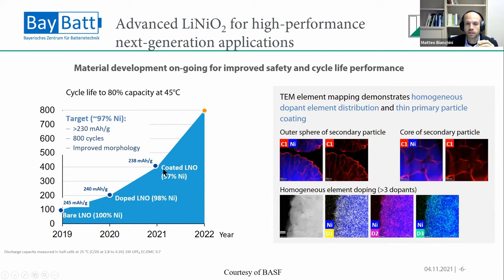And then what you absolutely need is also a coating. So as I mentioned before, you need something that will protect your surface from unwanted reactions. And this coating needs to be also highly engineered. So you don't only want to cover the surface of the secondary particles, but ideally you want to infiltrate the primary particles as well and be able to cover each and every primary particle to fully stabilize the material. So as you can see, by doing this, we have already quadrupled the cycle life and given up only a small amount of capacity. And of course, this is still ongoing and improvement of the materials continues. And hopefully something very close to this will eventually be a commercial material.